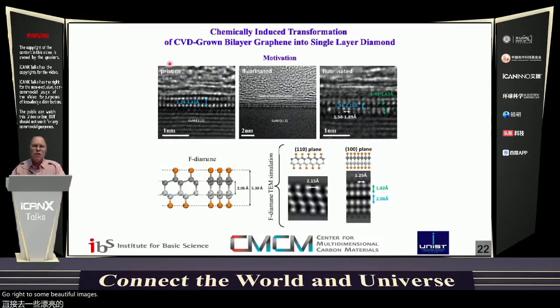So let me go right to some beautiful images that were obtained by Sokwu in Professor Zheng Hong Li's group. And on the left side here, you're looking at the pristine AB stacked bilayer with at any one point, you don't necessarily have exactly 3.35 angstroms separating the layers, but sort of averaged over, you would. And then as we fluorinate, we end up seeing very, very clear evidence in the cross-sectional TEM with the underlying copper nickel of the F-diamane. We could indeed observe from the TEM either the 110 plane or the 100 plane.